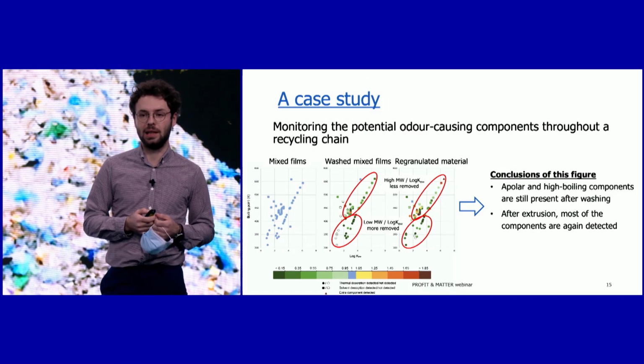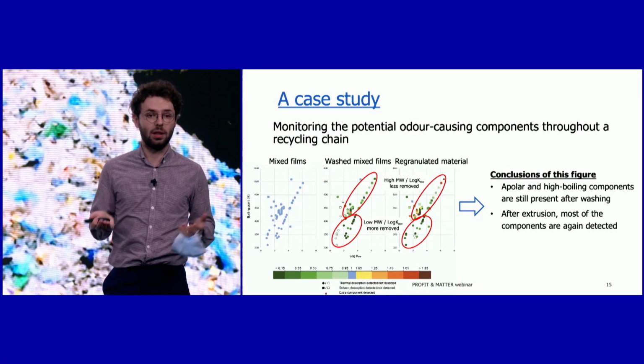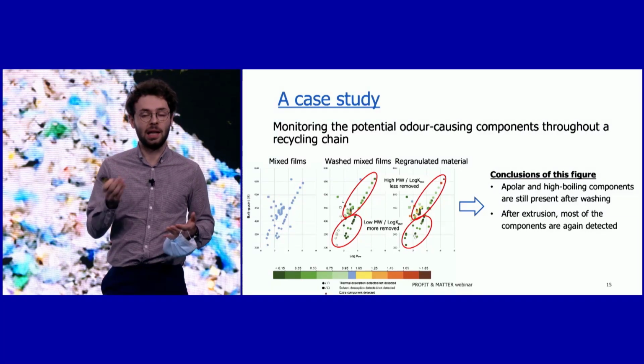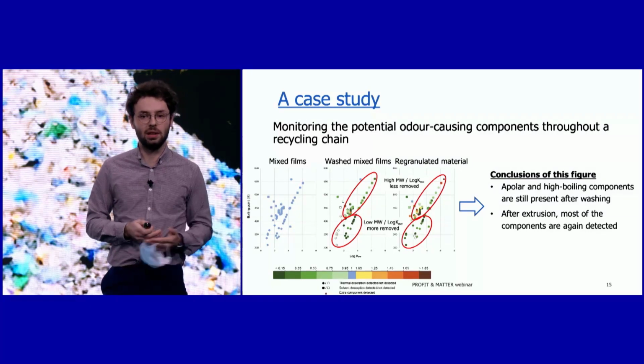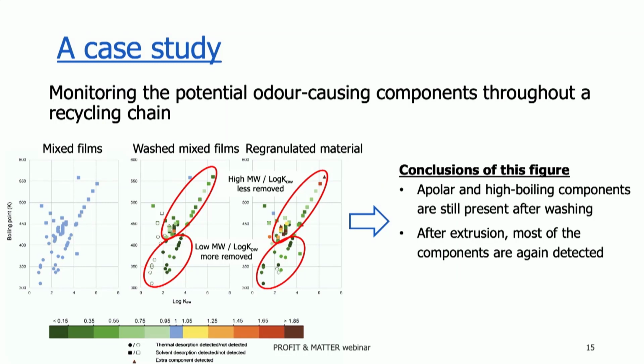Then, after the regranulation step, we see that certain components are present again, and even in a higher concentration than the initial concentration, as visualized in red on the slide. So the main conclusions here are that apolar and high boiling components are still present after the washing step, and secondly, that after extrusion, most of the components are again detected, and sometimes even in a higher concentration.